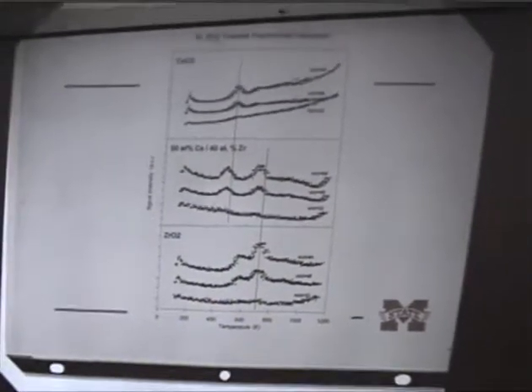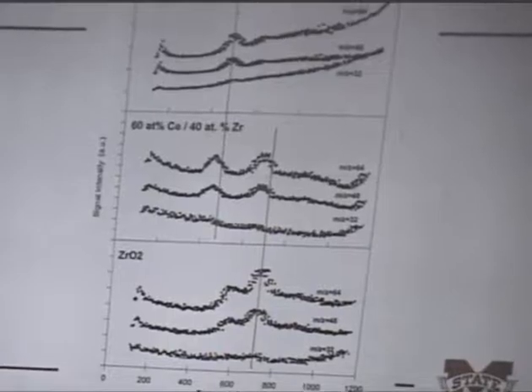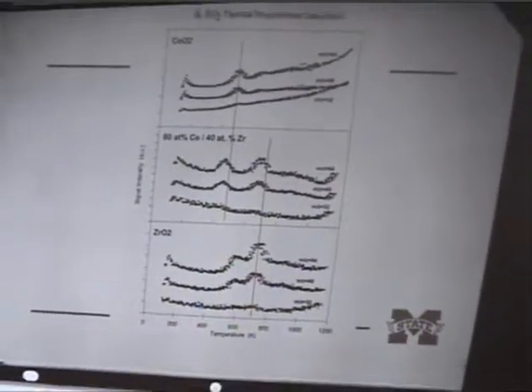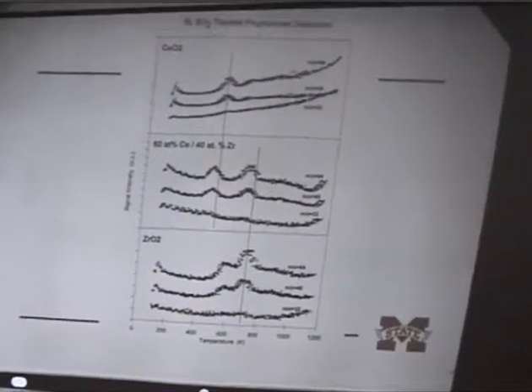For those of you who may not be completely familiar with this experiment, what we essentially do is we take our samples in ultra-high vacuum, we cool them down to 100 degrees Kelvin, we expose them to SO2 enough to get a saturation coverage, then we pump out the vacuum system while maintaining it at 100K, then heat it up with a mass spectrometer in front of it from 100K to 1000K and see what comes off.